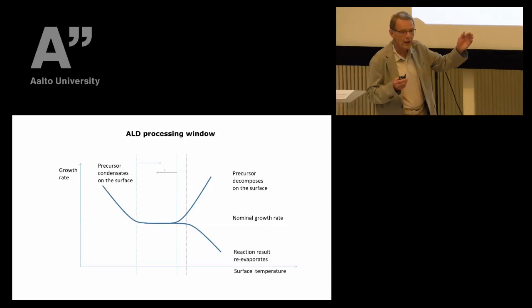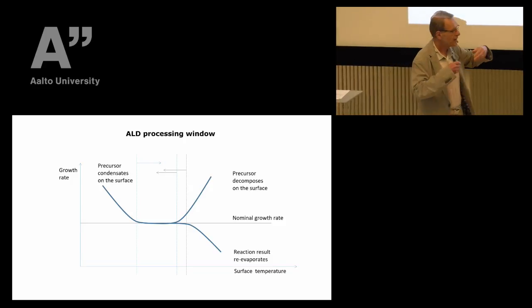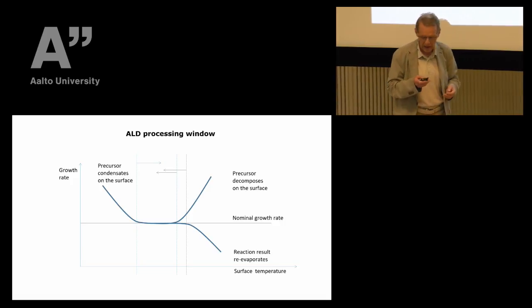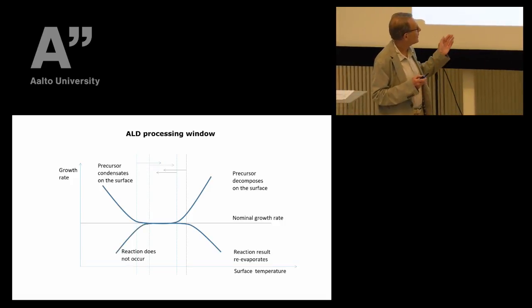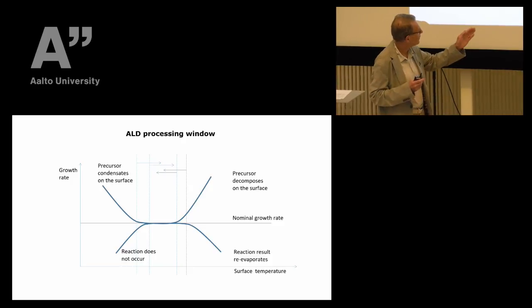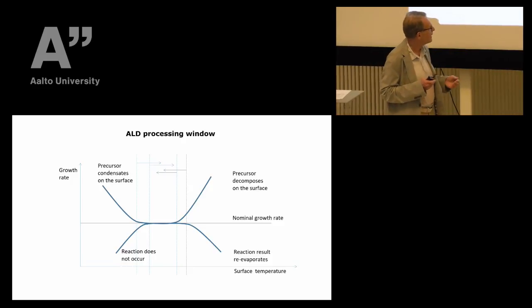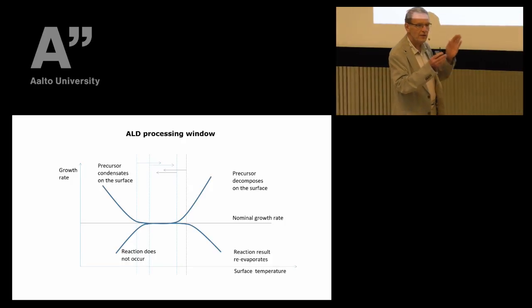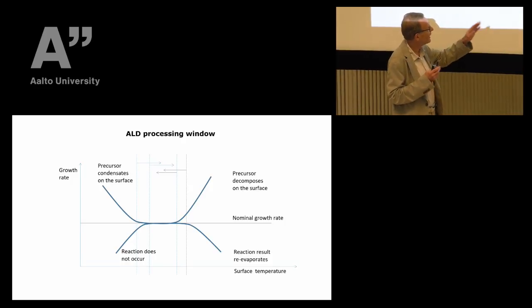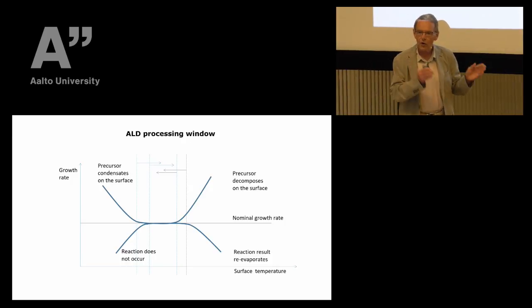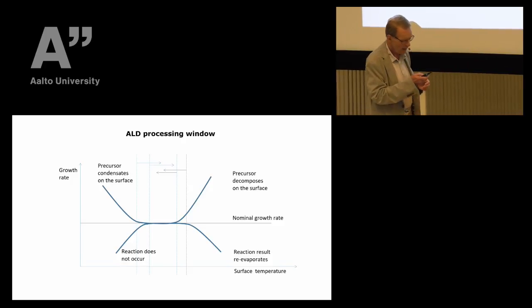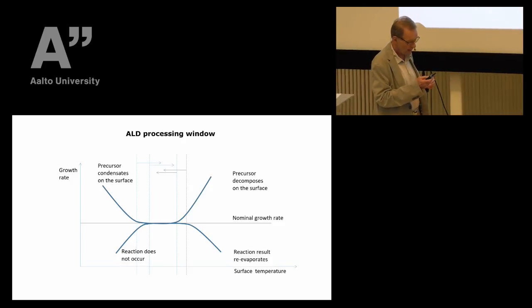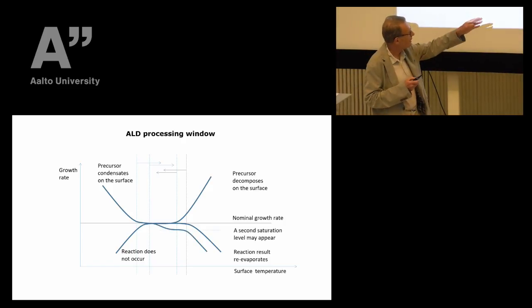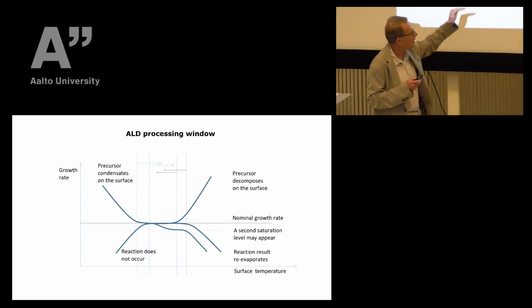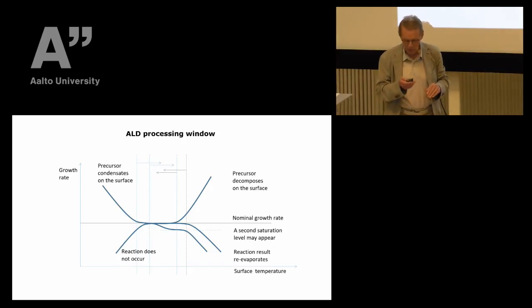If the temperature is too high, maybe our volatile compound decomposes and results in unwanted growth. On the other hand, we need a reaction temperature high enough to make the reaction occur. So there are several steps, and all these factors must be considered for each partial reaction, so each phase, for each reaction step. And in fact, the chemistry may be more complicated. There may be another saturation level also.